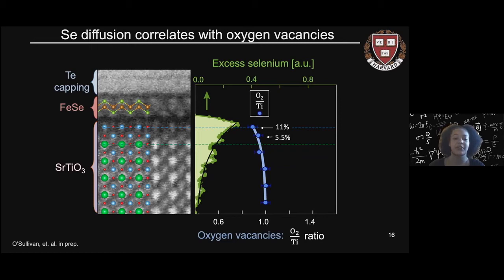We'll also note that the selenium decay into the strontium titanate bulk, as well as the decay of the oxygen vacancies, follow a similar decay shape. And the highest concentration of selenium diffusion is also in the area of most oxygen vacancy. So this suggests that it's possible the selenium is replacing oxygen vacancies in the strontium titanate bulk, and this is what's allowing for the diffusion. So this essentially motivates our result that selenium is able to diffuse because of oxygen vacancies.